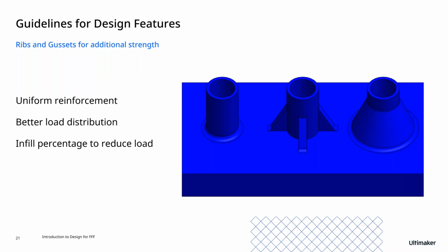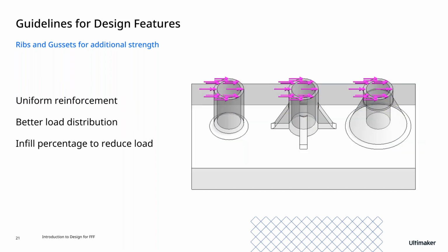The third option on the right produces the least amount of stress, but the thickness difference is big and gradual and will produce defects if injection molded. However, it is perfect for 3D printing. There are no stress concentrations because of better load distribution. We did a stress analysis to compare these results. Let's go ahead and look at them.